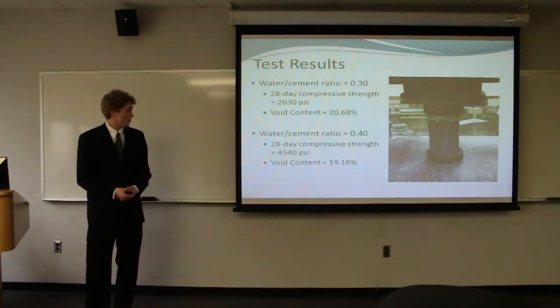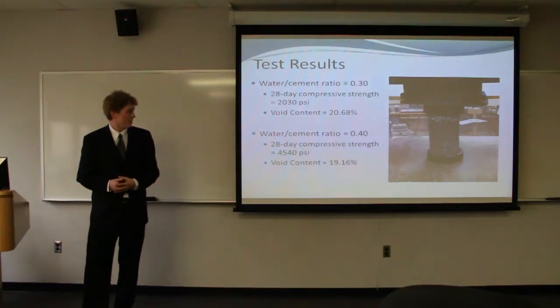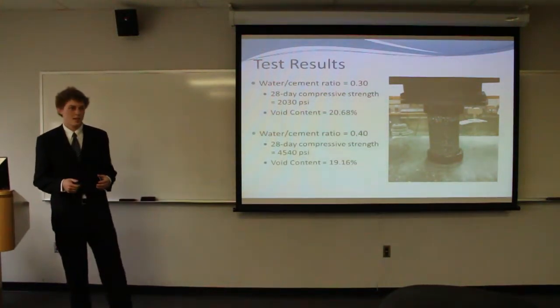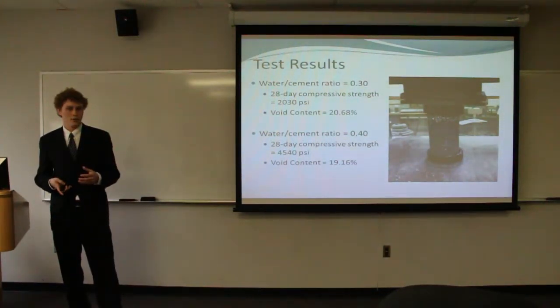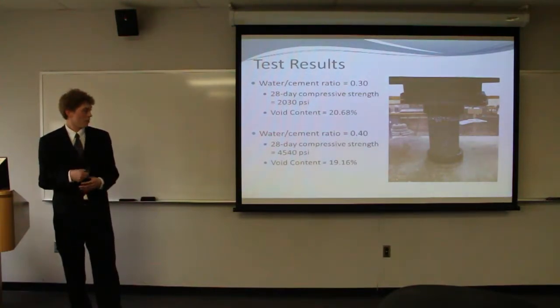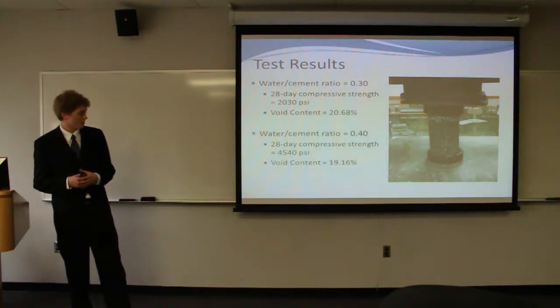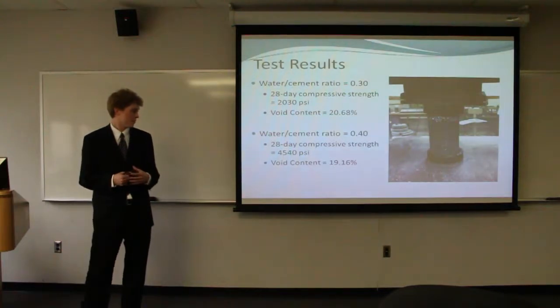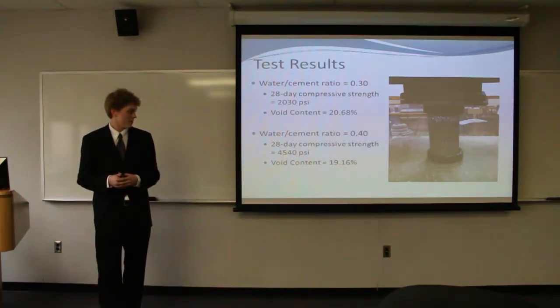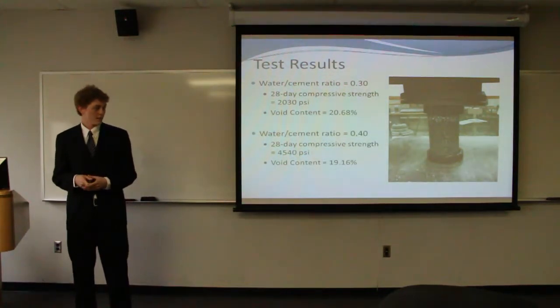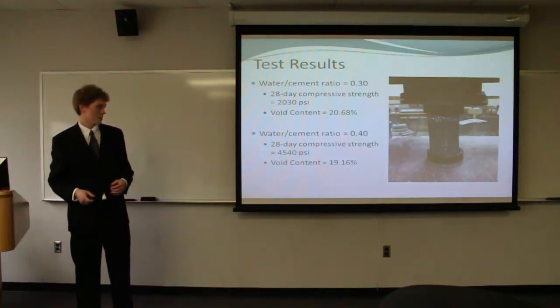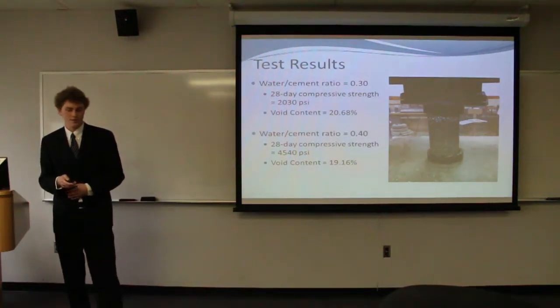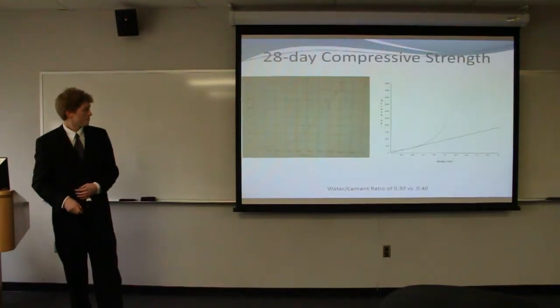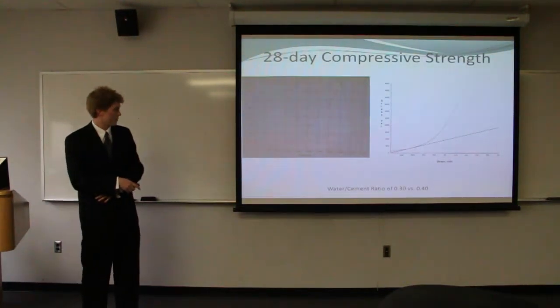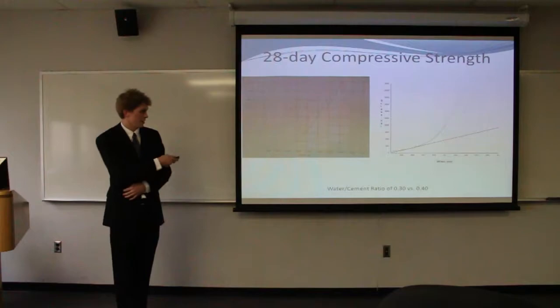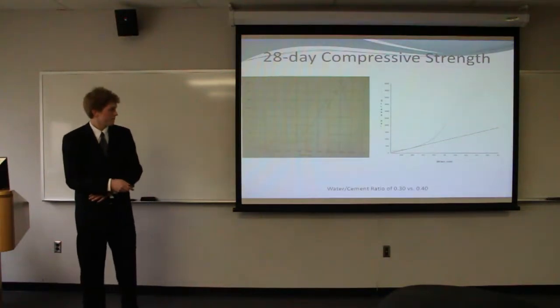So for the .30, we had a 28-day compressive strength of 2,030 psi and a void content of 20.68%. And for the .40, we had a 28-day compressive strength of 4,540 psi and a void content of 19.16%. And over to the right over there is just a picture of us doing the compressive strength test. Here's a look at the stress versus strain graphs for the .30, which is on the left, and the .40 on the right.